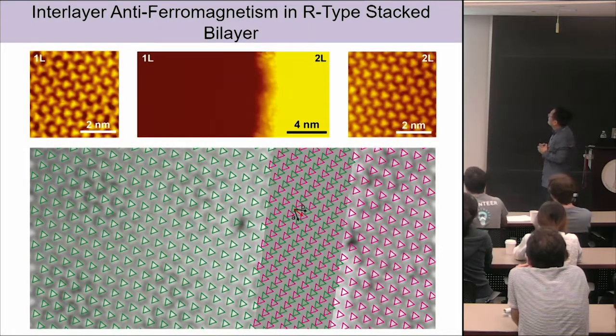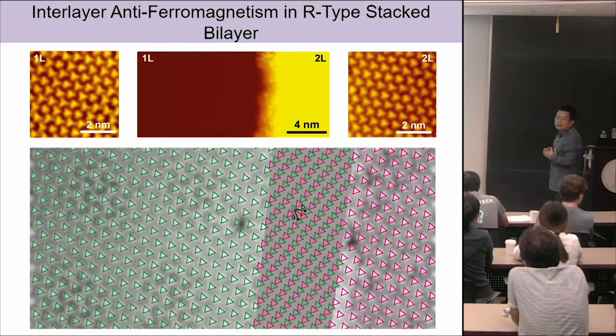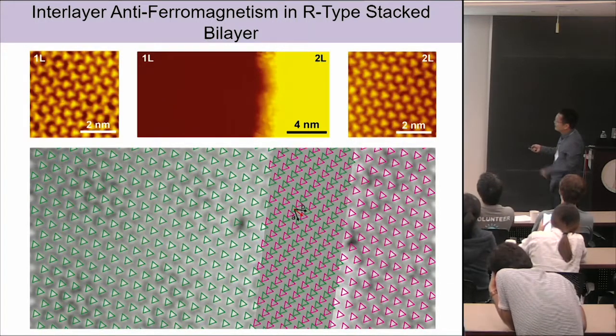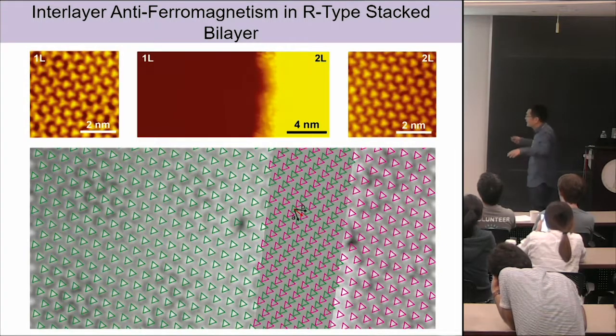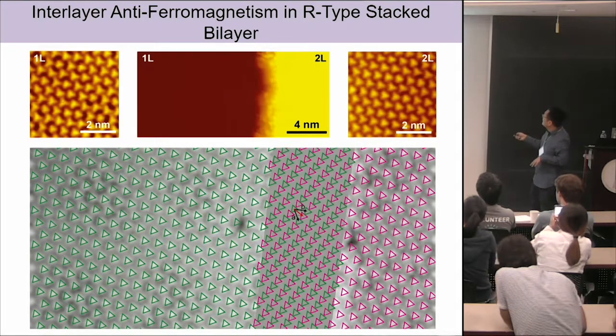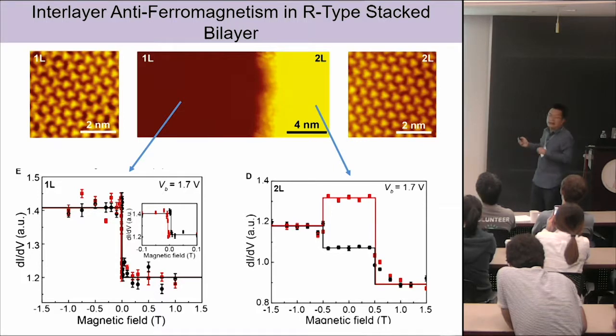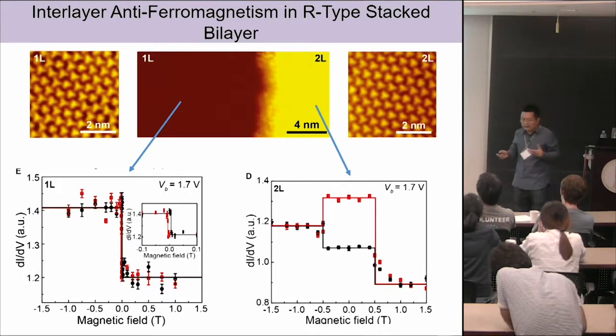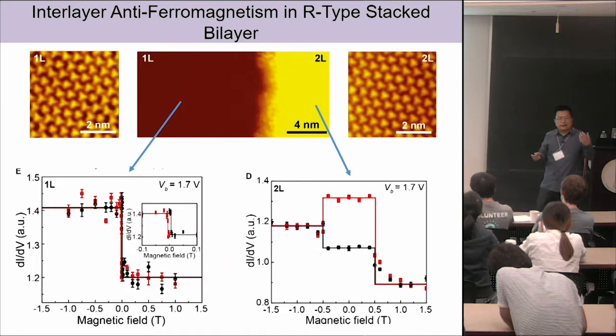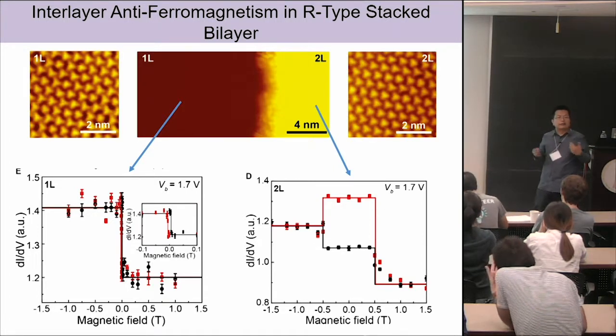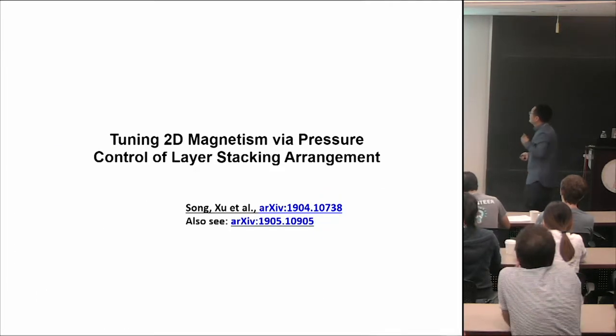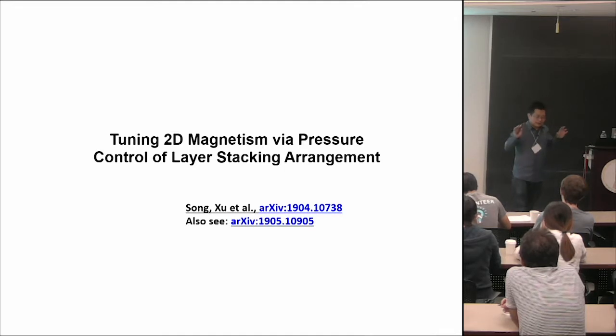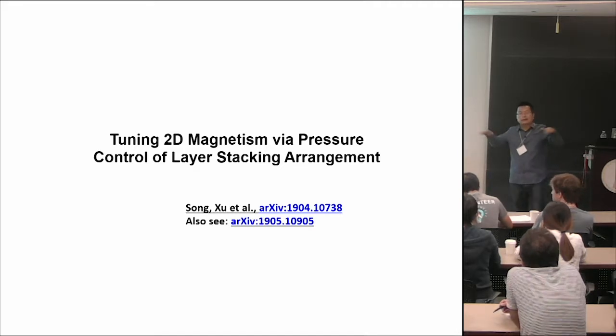But what's really interesting is they also found there's R stacking in coexistence, just random. So it's the same idea, right? You just measure the crystal structure, basically the orientation of these triangles for the top layer and the bottom layer, then you extend it, you figure out the stacking order for these bilayers, and it turns out to be R stacking. And in the R stacking, it turns out it's antiferromagnetic, right? So these are really nice results because we directly correlate these stacking arrangements to the magnetic orders. Okay, so now hopefully we established there's a correlation between the layer stacking arrangement and these magnetic orders.